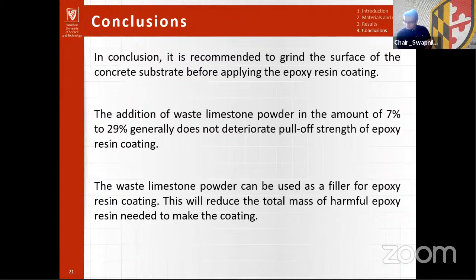The addition of waste limestone powder in the amount of 7% to 29% generally does not deteriorate pull-off strength of epoxy resin coating. So, the waste limestone powder can be used as filler for epoxy resin coating. This will reduce the total mass of harmful epoxy resin needed to make the coating.